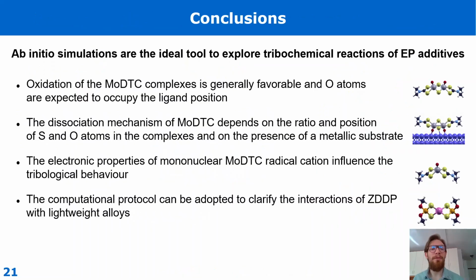So I hope I was able to show you the power of ab initio simulations in describing the tribochemistry of extreme pressure additives. So to summarize, we have seen the effect of oxygen on the isolated compounds, the decomposition mechanism of MoDTC on iron substrates. We have seen not only the catalytic effect of iron, but also the different tribochemistry of these additives depending on the position of oxygen in the molecules. We moved to describe mononuclear MoDTC and their peculiar electronic properties that have an effect on their tribological performance, and also that this computational protocol can be adopted to describe the tribochemistry of different complexes, for example ZDDP with lightweight alloys.